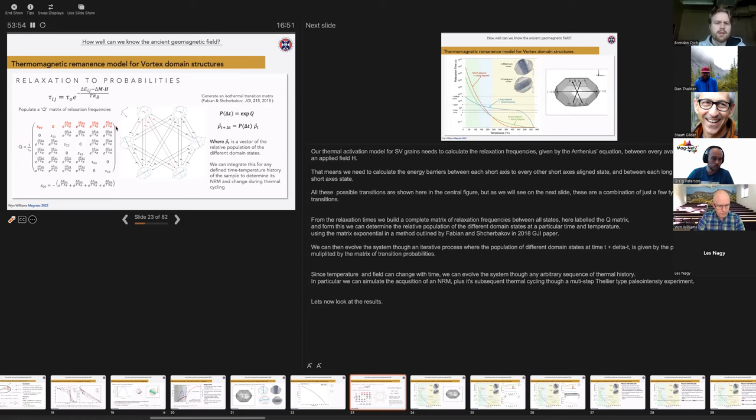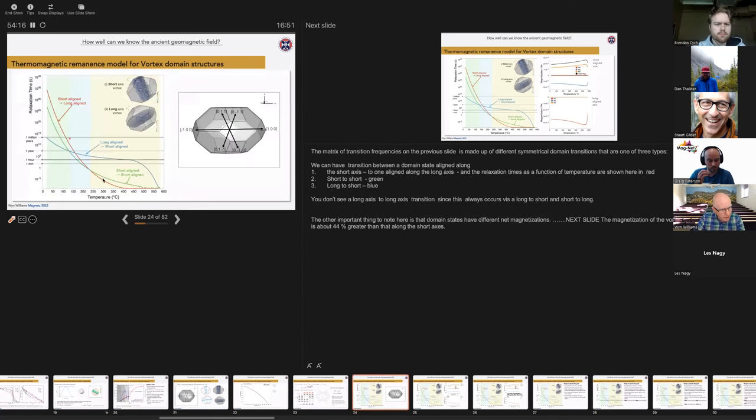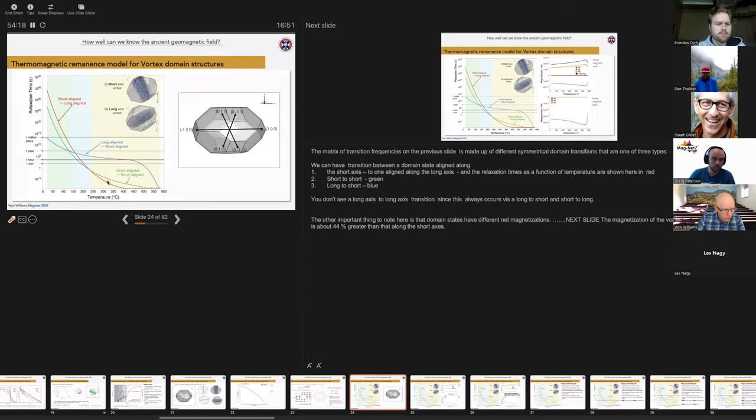I obviously didn't explain that well enough. I rushed too much. I can go through it very quickly again. So the cooling rate dependence really is embedded in this phase diagram of the domain states, because it depends upon, as you cool down, which type of domain state nucleates first and becomes stable first. You know, so at very high temperatures, you can see all these relaxation times are very, very small. So below about 500, everything is really tiny and everything is unstable as we might expect. And at fast cooling rates. So we could imagine that each of these temperatures are only sits at each of these temperatures for one minute. I mean, obviously in our simulations of NRM, we have a Newtonian cooling rate, but just as a very broad approximation here.